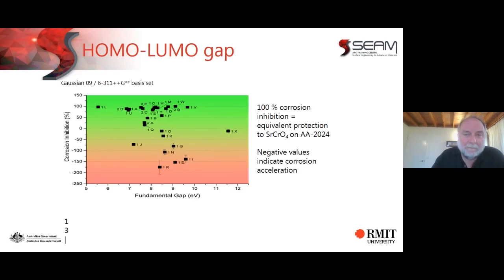One of the most famous molecular properties in the literature is the HOMO-LUMO gap. This is the highest occupied molecular orbital and the lowest unoccupied molecular orbital. The difference between that gap basically tells you, is the molecule electrophilic or not? Will it transfer its electrons to the metal surface and therefore bind to the metal surface? It was considered by many researchers that that would give us a very strong indication of whether the corrosion inhibitor would work or not. So we tested that with our expanded database generated by the more rapid testing and the more rapid molecular modeling.